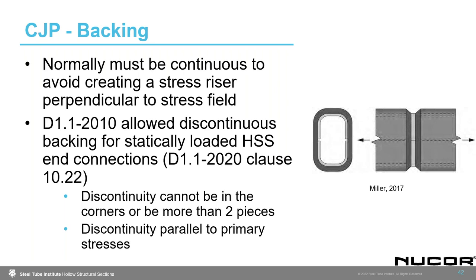It cannot be more than 2 pieces. So you can basically have 2 pieces that go inside and perform that backing. And the discontinuity has to be parallel to the primary stresses. So those are 2 provisions that have to be met if you're going to have discontinuity for your backing for an HSS at its end.